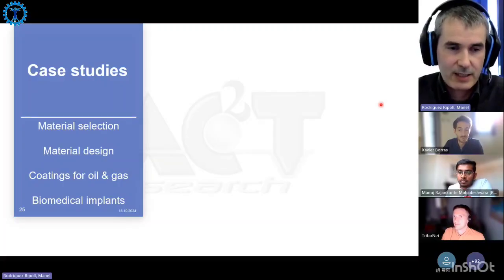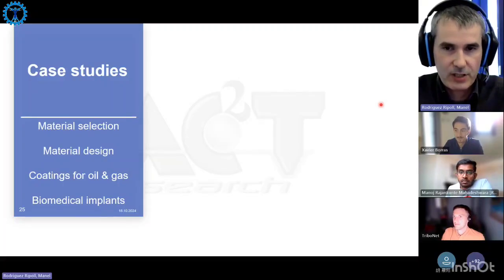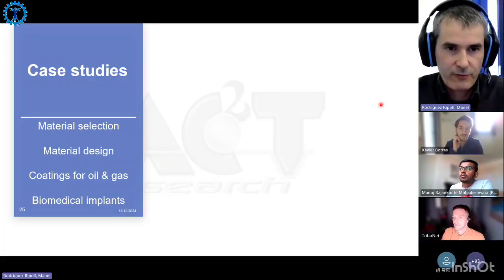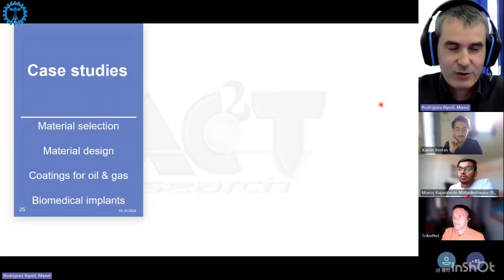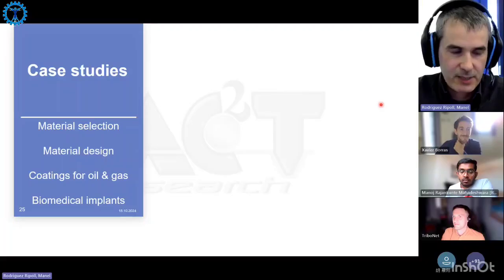The anode is the outside of the wear scar and the cathode is the inside of the wear scar. So in some of these metals, like these colleagues show for carbon steels, during tribocorrosion you're actually accelerating corrosion outside the wear scar. But that's a bit of a different story with active metals to what I showed today. So you can still use the same tools, but the concepts are a bit different because you don't have this concept of depassivation. There is still this galvanic coupling, but it's different.